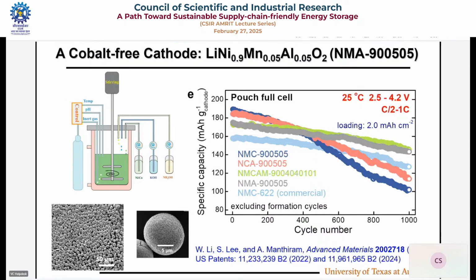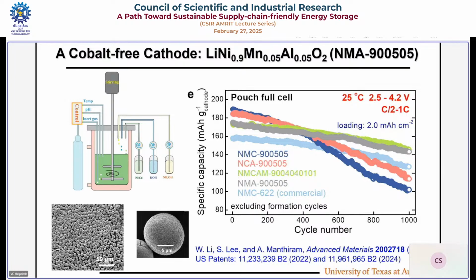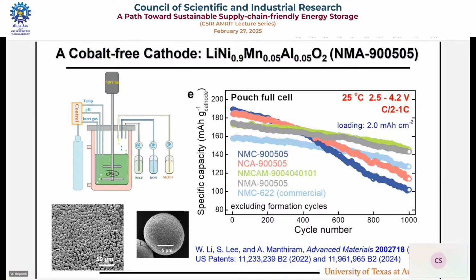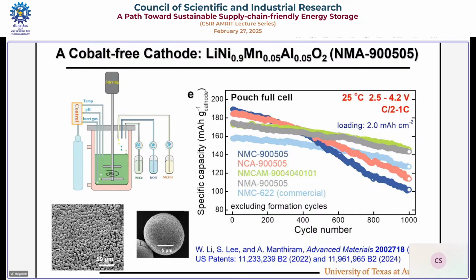Silicon has a big volume change, so you cannot use bigger particles; you have to use nano. If you use nano layered oxide, you have huge surface area and huge reactivity, with side reactions with the electrolyte. There will be a lot of solid electrolyte interface layer. It will not work, so they have to be made as 12 micron secondary particles, or 10 micron like you see here.